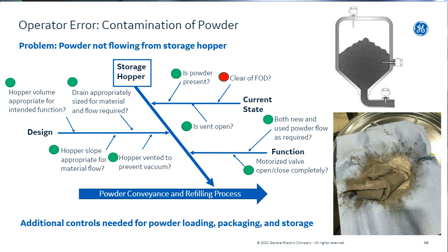Only one. Every bottle comes with it, so it was just one of those operator oversights of not necessarily looking at exactly what they're doing, but you've got to prevent that. I mean, what if you look away for 1 second and the desiccant goes in there and the build has stopped because powder's not able to get into the machine?